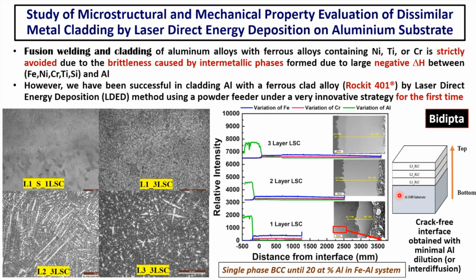So what she did was to take aluminum substrate and deposit Rockit 401, a trademarked ferrous clad alloy, in multiple layers. And the process parameters - the entire trick was that the process parameters were chosen so carefully that you melt a marginal amount of aluminium when you deposit molten clad 401 alloy on top of aluminium.